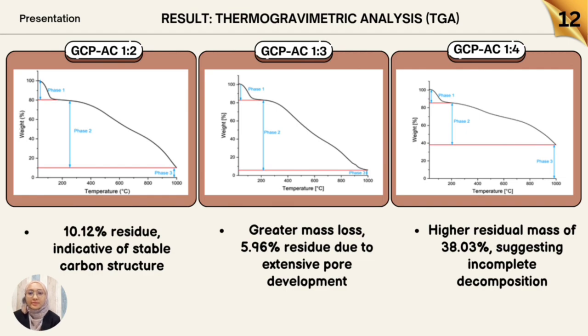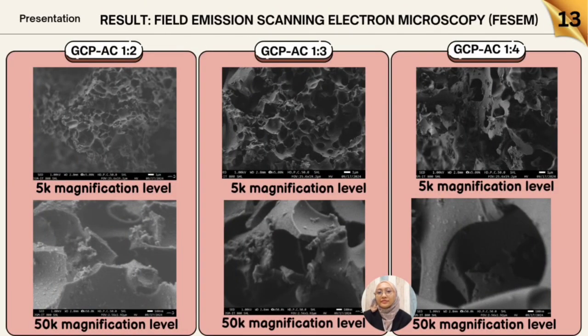Results for thermogravimetric analysis, which is TGA. TGA analysis indicated that the 1 to 3 sample exhibited the most effective activation with a final residue of 5.96%, indicating optimal thermal stability and pore development. In contrast, the 1 to 4 sample showed a higher residue of 38.03%, suggesting incomplete decomposition and more retained inorganic compounds, while the 1 to 2 sample showed 10.12% residue, indicative of stable carbon structure.